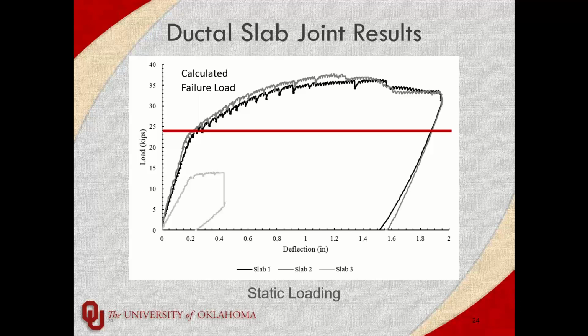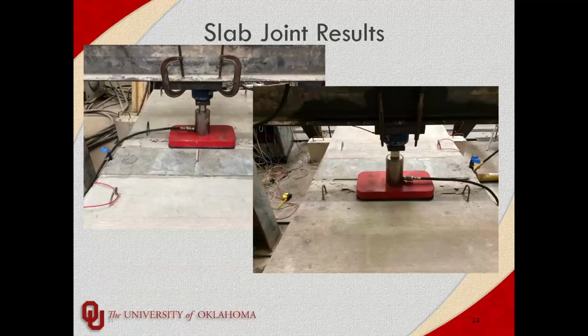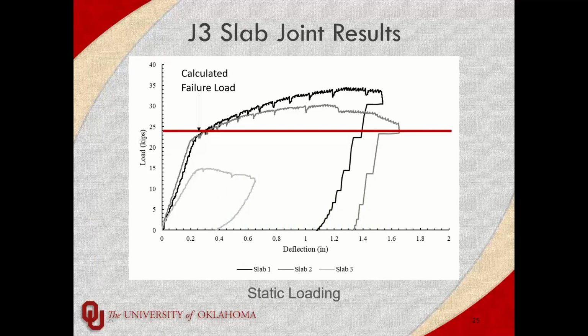This is a plot of all of the static tests that we did on Ductal. The first 2 big ones are the regular slabs where we didn't do any cyclic loading before. That calculated failure load was the estimated failure load for just a monolithic conventional concrete slab. So we did exceed the strength in all of those, which is great. And we got a lot of ductility out of the Ductal slabs. And then the cyclically loaded test was that bottom little plot. It obviously didn't reach as high as the unloaded slabs, but you did get a little bit. I was a little surprised at the ductility we got out of that. I presumed it would have just popped because we took it, I believe, up to 5 million cycles even after increasing the load. Next slide.